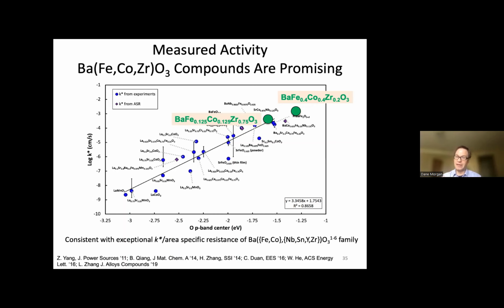But we predicted that it would help with stability and it would still allow enough electrical conductivity that you could have a promising material and it would keep good surface exchange, which was really counterintuitive to most of the people we talked to. In fact, it was counterintuitive enough that they insisted on making a lower zirconium content as well, because they didn't really believe this was going to work. But once we made it, this is the actual measured surface exchange coefficients that we obtained from an experimental effort. This is a collaboration with the National Energy Technology Laboratory.